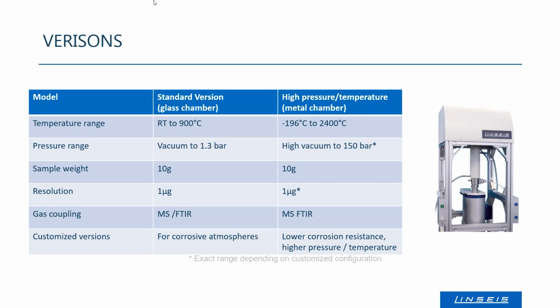The standard version is made out of a glass chamber, so it's really resistant to almost anything besides hydrofluoric acid, which is a critical part, but anything else could be measured. And then we have a high pressure version, which is made mainly of a metal chamber, that goes from -196, so from liquid nitrogen, up to 2400 centigrades. It can operate now up to 150 bars. So it depends a little bit on the temperature range what the maximum possible pressure is. It's the same balance unit in general, so the same sample weight, the same resolution. Again, the resolution depends a little bit on the pressure and temperature range, so it may be a little bit worse depending on the maximum setup you have.